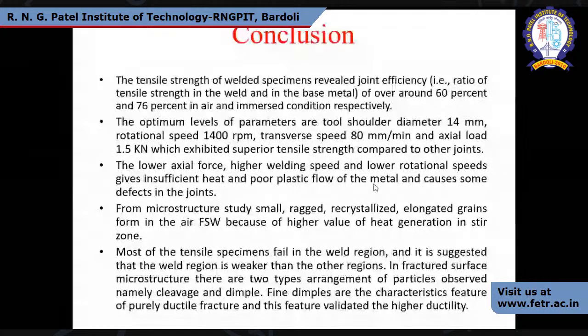The last conclusion is that the fine dimples are characteristics of purely ductile fractures, and these features validate the higher ductility in the case of the microstructure effect. So these two types of arrangement, air FSW and immersed FSW, give us different results. These are the conclusions of what I did in this particular FSW process.